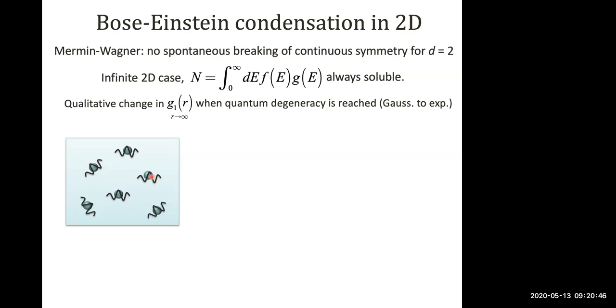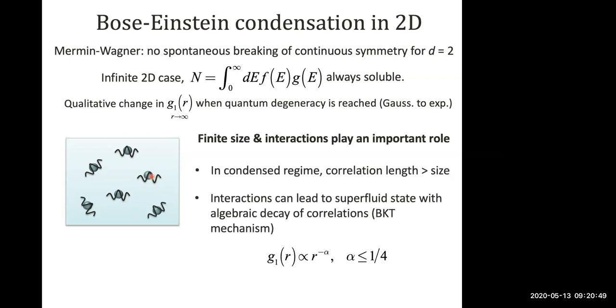And in the systems we'll be considering, we typically will consider a finite size system. So if you have a finite size, then you can have a condensed regime. And this more or less corresponds to the situation where the correlation length is equal to the system size. This is very close to the density where you would reach quantum degeneracy in most cases.